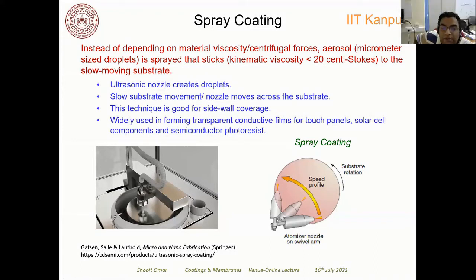Okay. So this spray coating technique is not using the centrifugal force, but it depends upon the aerosol quality which is formed and that is sprayed on the substrate. Now, in this particular case, you can see nozzles are there, right? So, nozzle is there, through which the liquid is flowed, and the aerosols are formed. These droplets are getting deposited on the slow-moving substrate. In certain variants, these nozzles are rotating, while in other variants, the substrate moves. But this technique is good for side wall coverage.